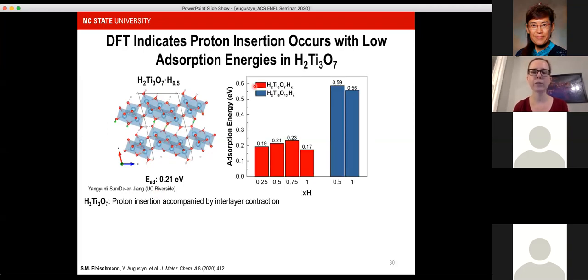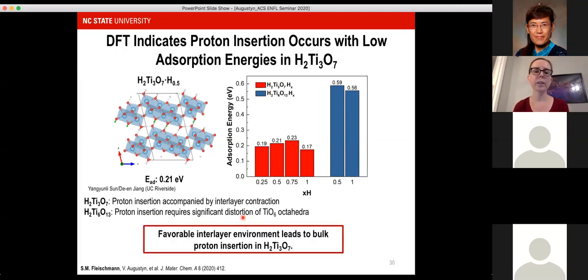On the other hand, if we compared those absorption energies to the next structure, those absorption energies increased, more than doubled, and that was associated with a more significant distortion that had to take place to accommodate the protons. So this was another example now through metastable synthesis, soft chemistry routes, to favorably tune the interlayer environment to enable bulk proton insertion in the hydrogen titanates.